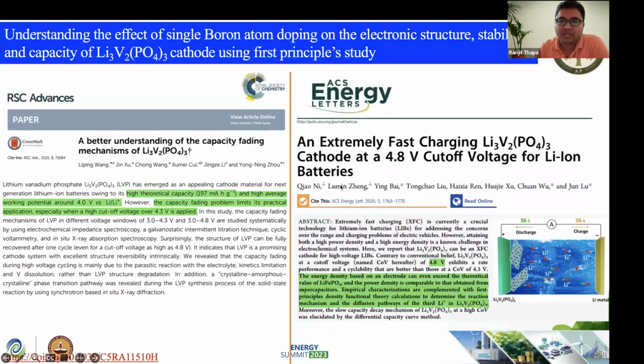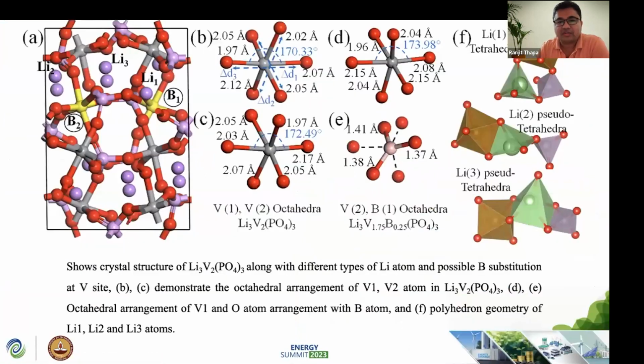There are a lot of works on this, and we have taken one example, LVP. This is one of the materials which is very well known. So we have taken this, and then we have tried to understand why it is not happening. This is just an introduction of the same work. We have seen that this lithium vanadium phosphate, LVP, has 3 types of lithium: L1, L2, and L3. Because of their coordination, their environment, and their different nature of tetrahedral bonding, they behave differently, or how they will behave if I put any other foreign element. That is the concept. And which lithium is having the obstacle to 3 lithium de-intercalation? So this was the concept, and then we have addressed this.